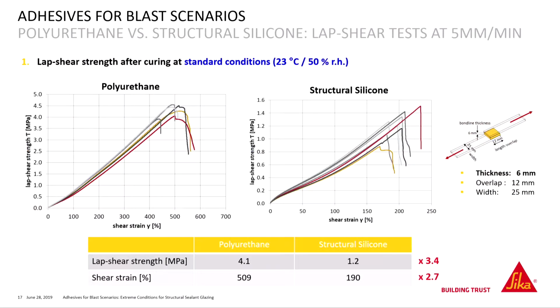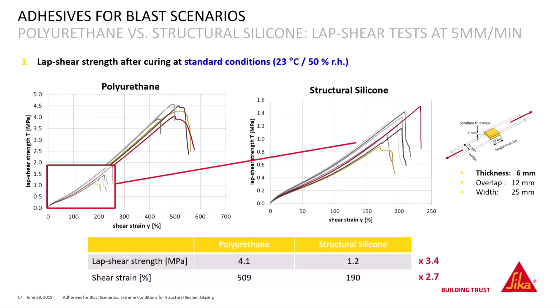So we have done a lot of tests, and first of all, we ran them under standard conditions. If you look at the structural silicone and the polyurethane, it does not look very different. But when you look at the right ratio here, silicones are working here, and this is the end of the polyurethane here. So that's quite a big difference, and I think it's worth doing more investigations on that.